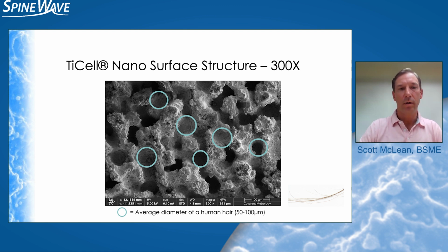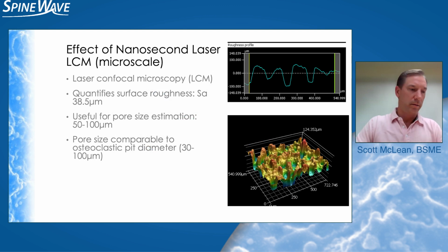So we're going to now look a bit at how we quantify the size of these features on the surface. And at this scale, the micro scale, we use a laser confocal microscope, and that quantifies the surface roughness for us. And that's really useful in monitoring quality, that we have the same features from device to device. This is a very rough texture with an average roughness of 38.5 microns, which is similar to a heavy grit sandpaper feel. This technology is useful for estimating the size of those pits and pores, as we said, by tracing a plane through the surface. We can deduce the size of those pits and pores, and we estimate those pores to be about 50 to 100 microns in size. Again, replicating the size of the osteoclastic pit very closely.